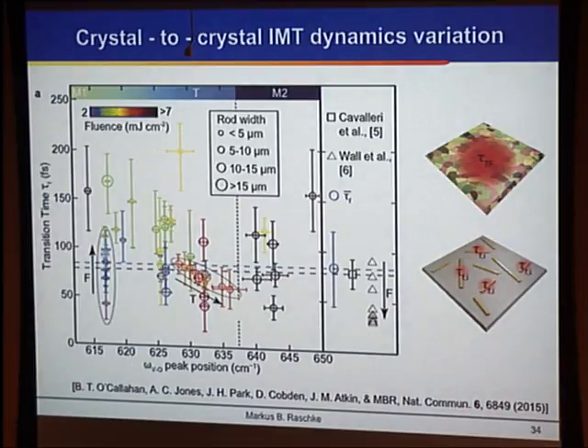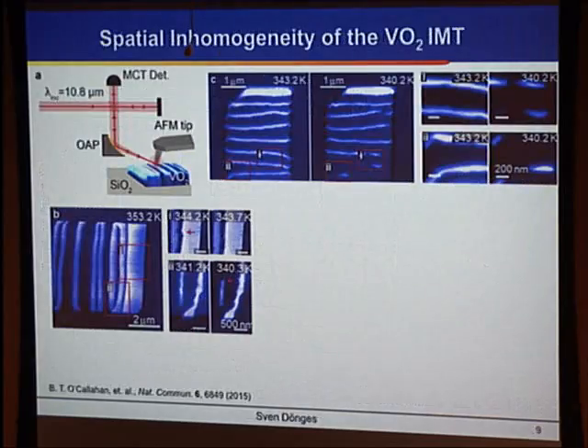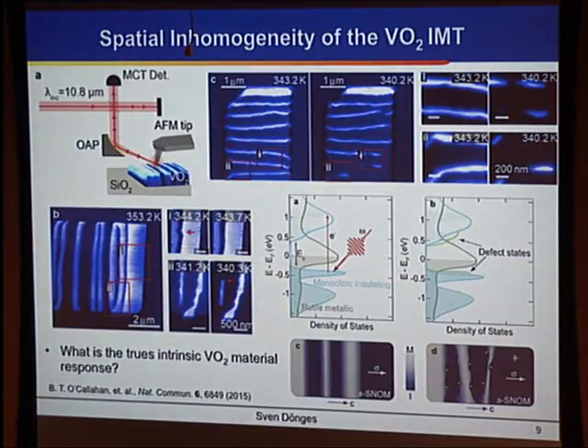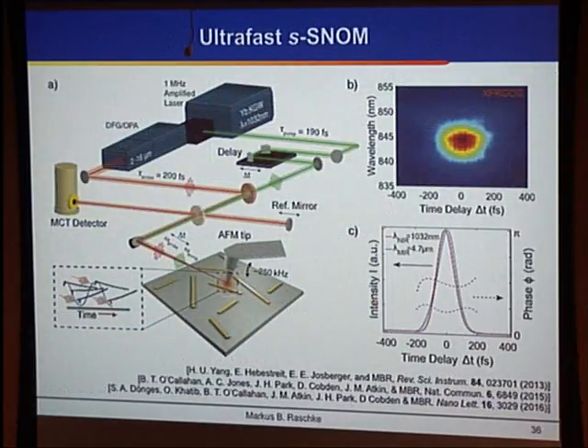And so this is what triggered us to say, well, we need to do local probe spectroscopy to look at what really happens at these domains which emerge as we undergo this insulator-to-metal transition, which we can nicely resolve with scanning probe imaging as we change the temperature. The idea was that we potentially have defect states populating the band gap, and we are either pumping into or out of these defect states, which then potentially inhibit or accelerate that transition into this metallic phase, which could be responsible for this large heterogeneity in the dynamics which we observed earlier. And so this is why we do near-field pump probe measurements.